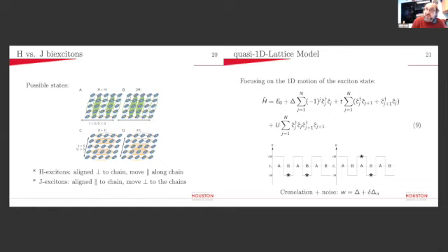If you take a one-dimensional Hubbard model that I show here in equation 9, and you drop off the last term with U, you simply have motion along a lattice. The delta I added to emphasize that if we're dealing with a copolymer system, you have an energy offset between site A and site B, which at the time I thought would be interesting to look at. I refer to this as the crenellation of the potential surface. It's simply the fact that you're dealing with a copolymer system that might have an energy barrier between the different sites.